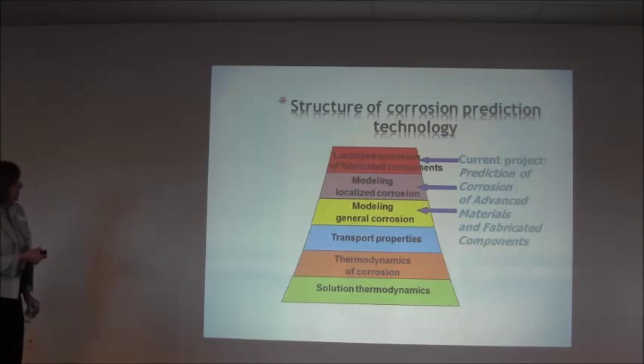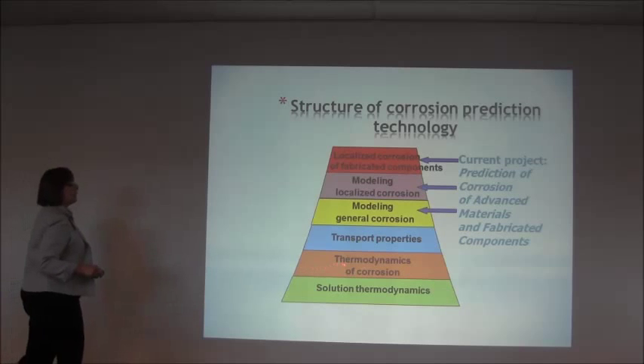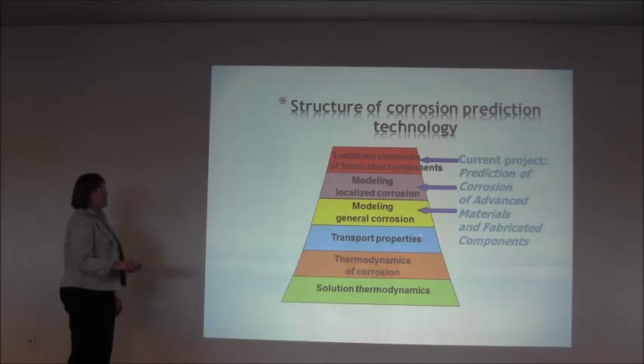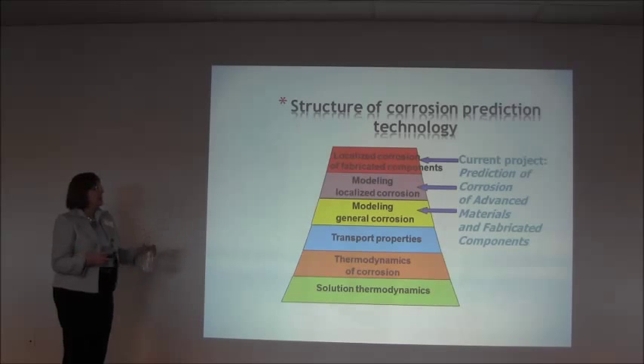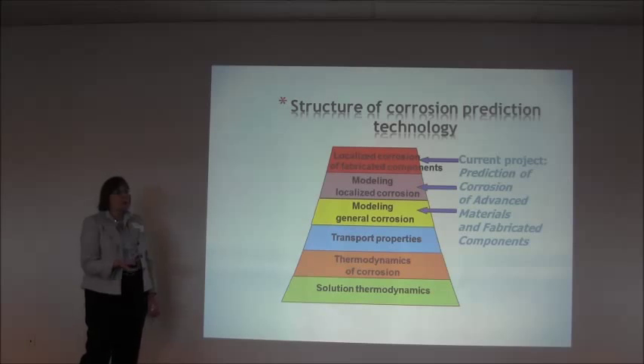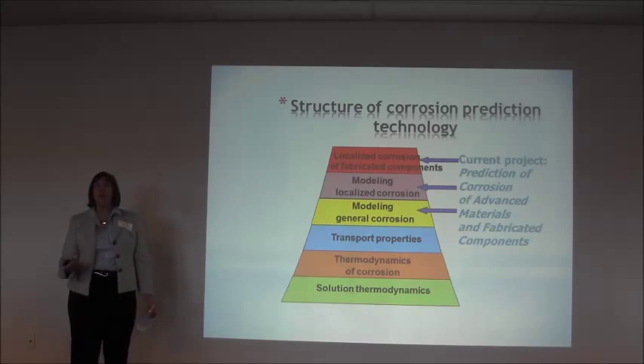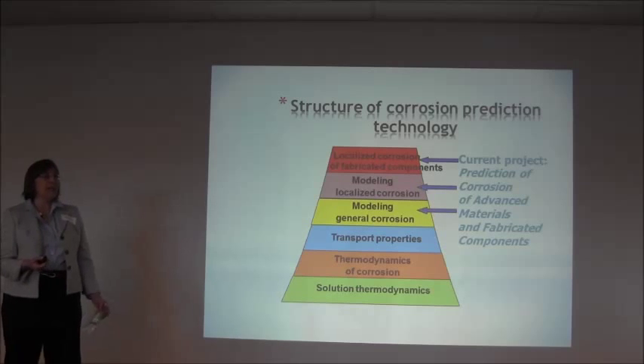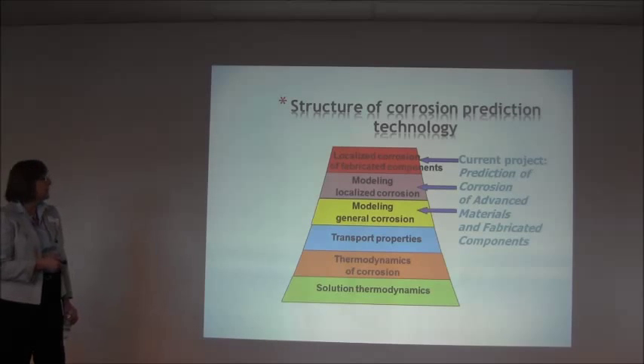Okay, let's go back to our tower of power. OLI says, first understand this chemistry. Then understand what's active, what's passive, what's corrosive, and what's inert. Then understand transport properties, so that you can understand diffusion between the bulk solution and the contact. If you do these three things, transport properties, thermodynamics, and thermodynamics of corrosion in solution, those are a first principles corrosion model. So what are we looking for with OLI electrolyte thermodynamics? A first principles model.